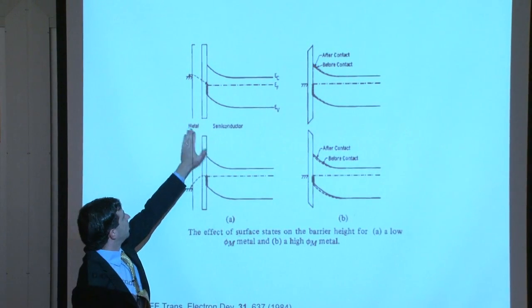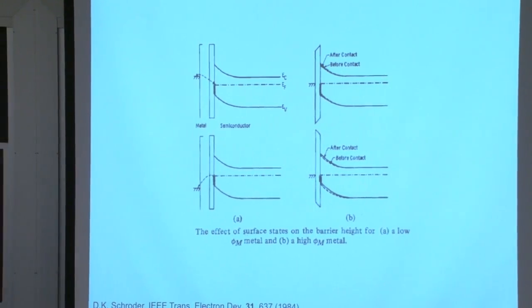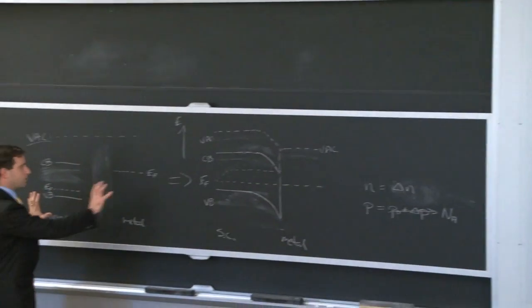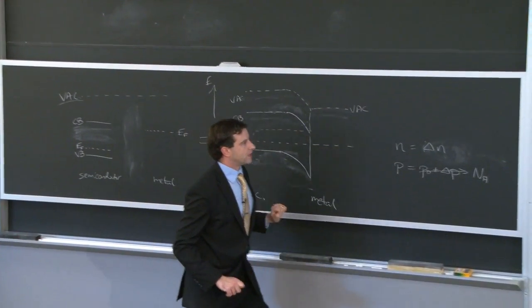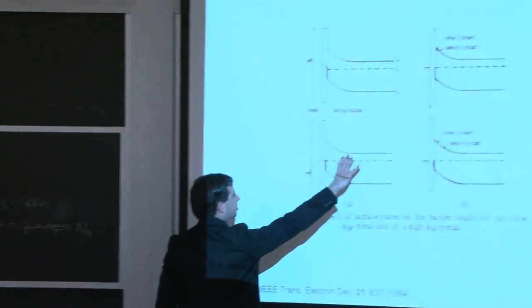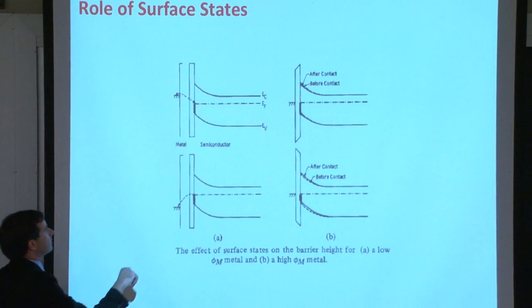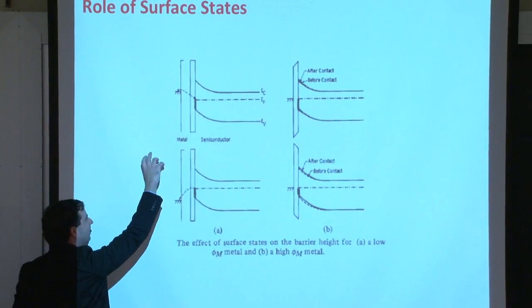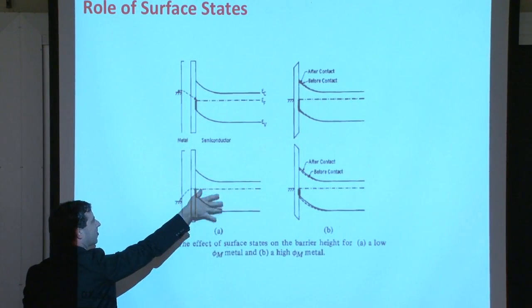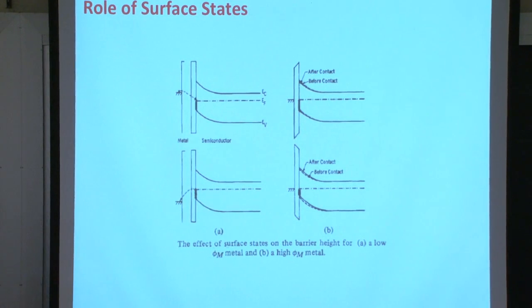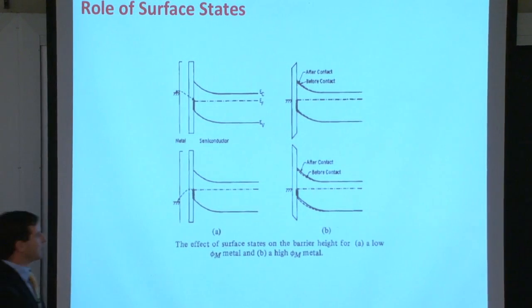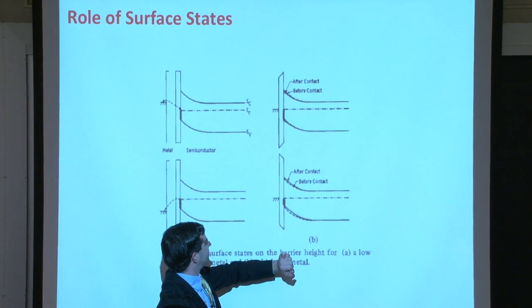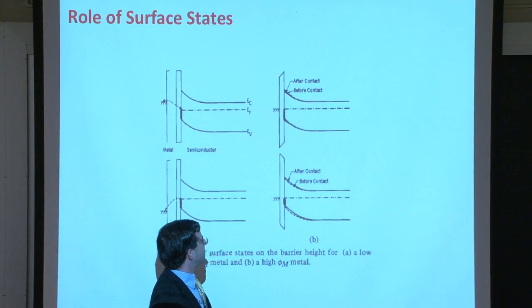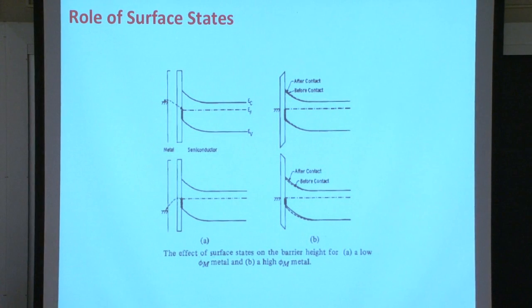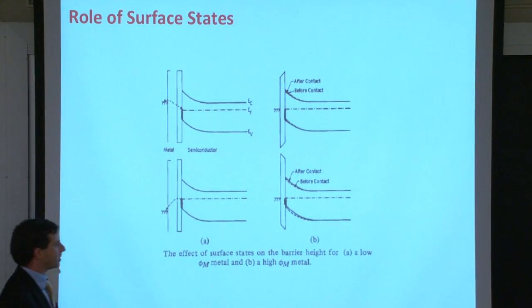And so given what we've seen before, given the Schottky method of producing the band diagrams here, we would expect that in this case, we would see bands bending, say, down. And in this case, we see band bending down in the semiconductor. And in this case, the bands would bend up in the semiconductor as we reach that interface. But because the Fermi energy is pinned by these surface states here, we have very little motion of those bands. And so we wind up in a case where we pin the Fermi energy at the surface.